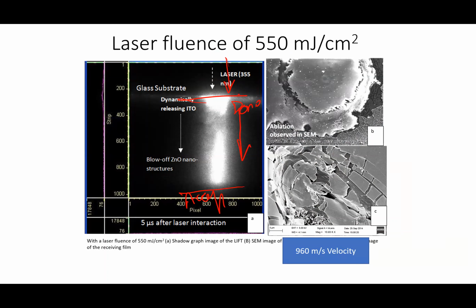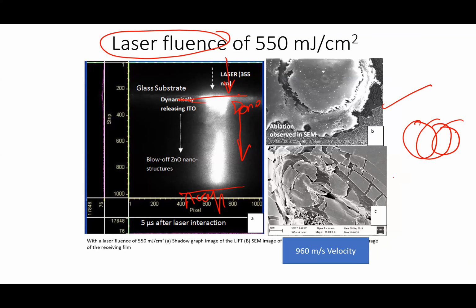The major parameters involved are our laser fluence as well as our spot overlap. These take care of the transfer of the particle from the donor region to the acceptor region. In this case, the laser fluence is quite high, around 550 millijoule per centimeter square, which results in a very high velocity. Because the particle moves at such a high speed, it will damage the acceptor and the donor.